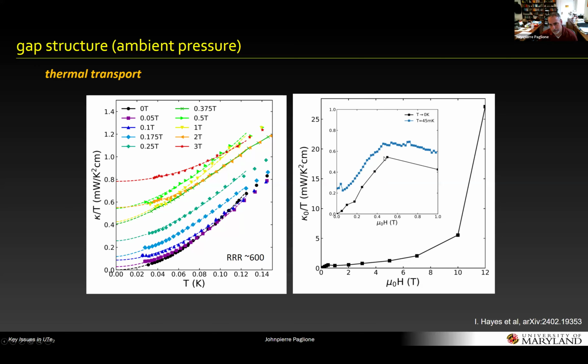But there's this maximum that turns over, and we're still studying what this maximum is about. We believe it's a crossover from the rapid rise due to the Volovik effect over towards a mixed state vortex regime, but we're not sure about that.